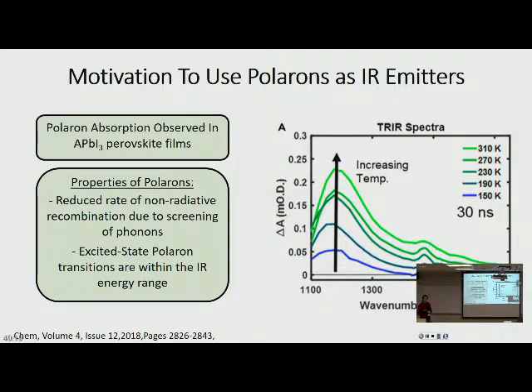a spectrum with different temperatures. Is it known if there's an ideal temperature, or is it hotter the better, colder the better, or is it like not as good and then you heat it up some and it gets better, heat it up some more and it gets worse? I think the higher the temperature, the more polaron formation there is. But then wouldn't that contradict the lattice, because then the lattice has more vibrational energy, so then it can, by chance, get away from where you have dipoles forcing charges into one location?